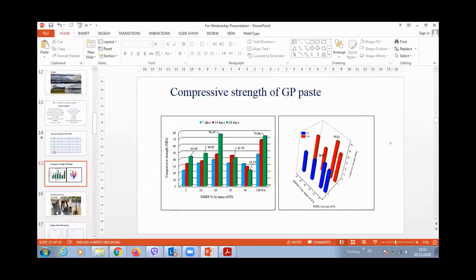So, a result as shown in this figure is the compressive strength of the geopolymer paste in comparison with the reference of 100% fly ash, with a different percentage of GGBS and magnesium slag. So it's very clear that the 28 days compressive strength obtained for our paste in the left hand is the highest value when it's loaded with GGBS, and then when converted and loaded with high magnesium slag. The optimal formula we obtained is from the GGBS loaded with the high magnesium slag. It gives us 10% from the magnesium slag, which gives the high compressive strength of 60 megapascal in 28 days.